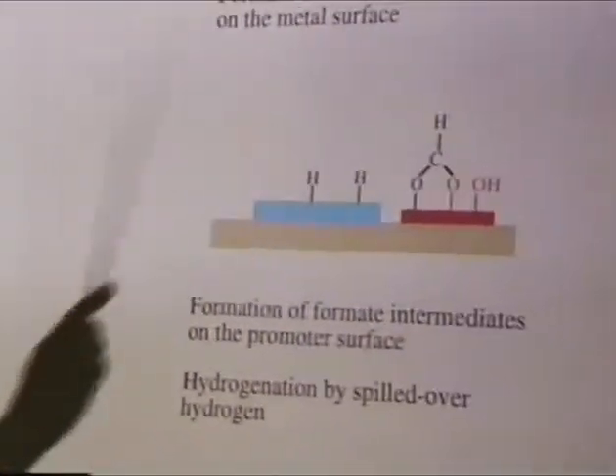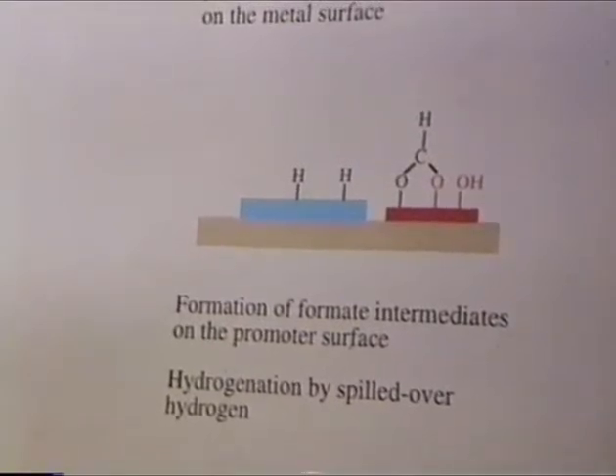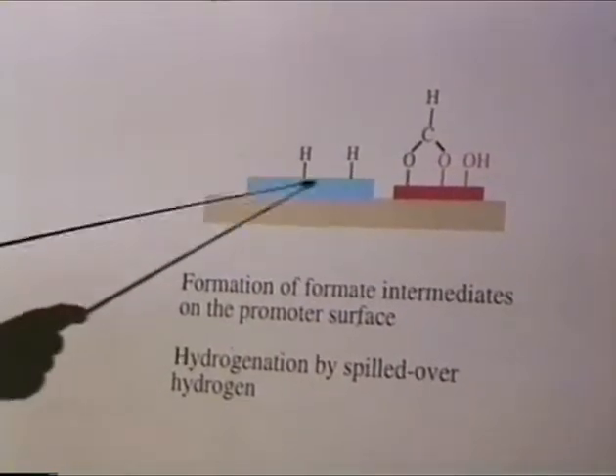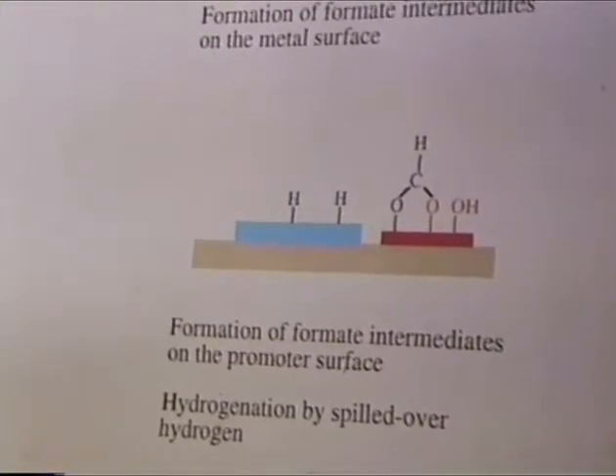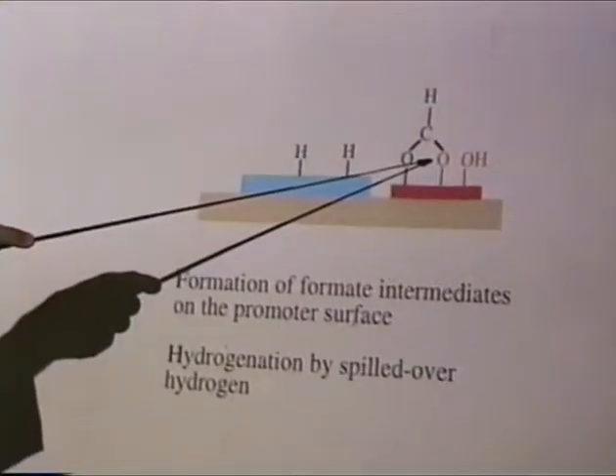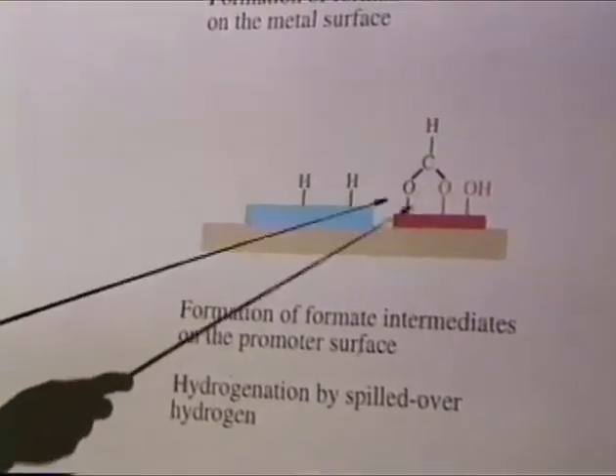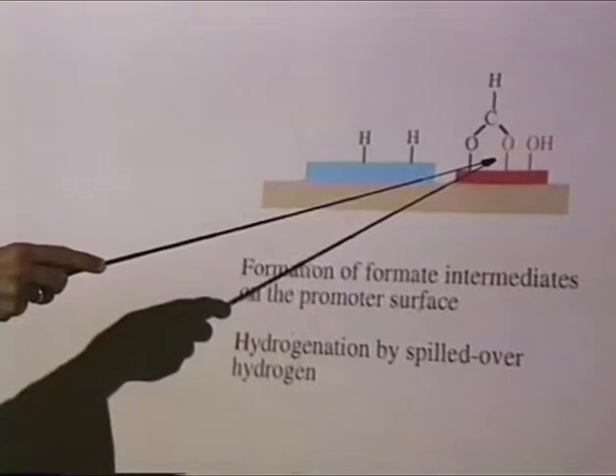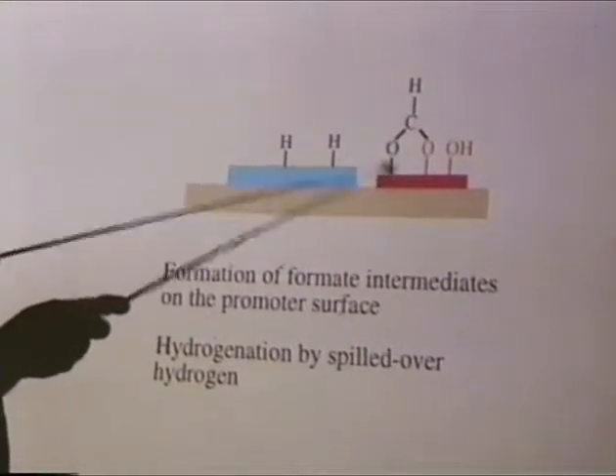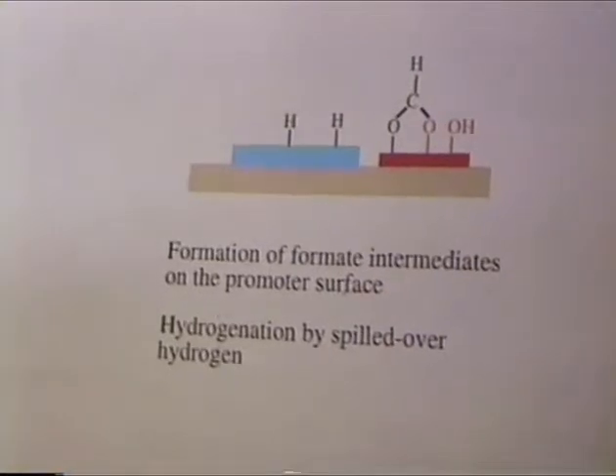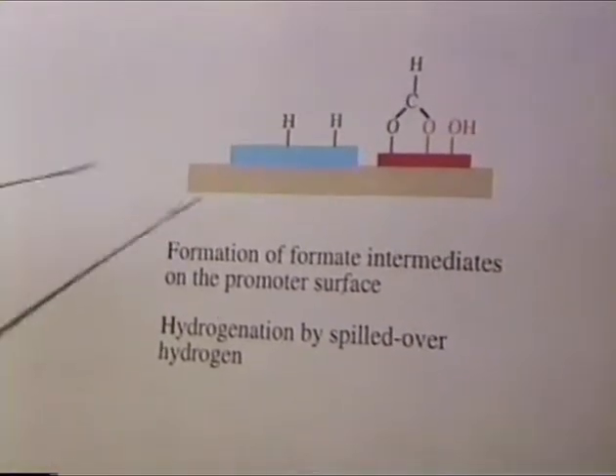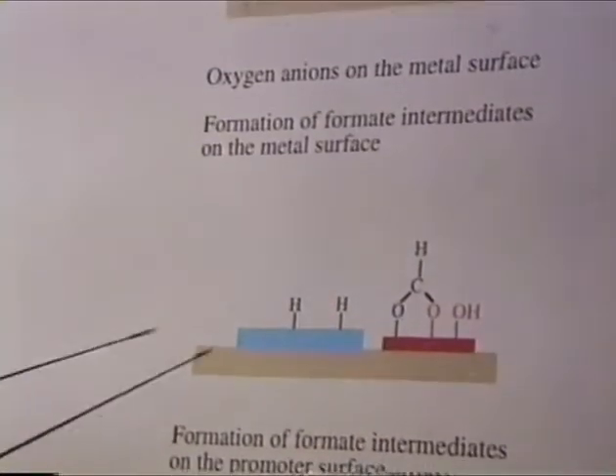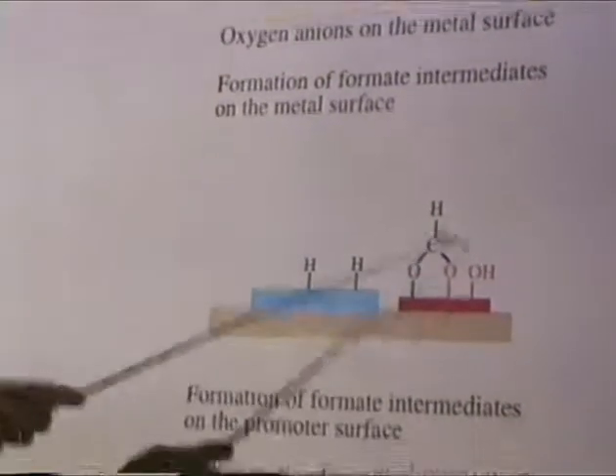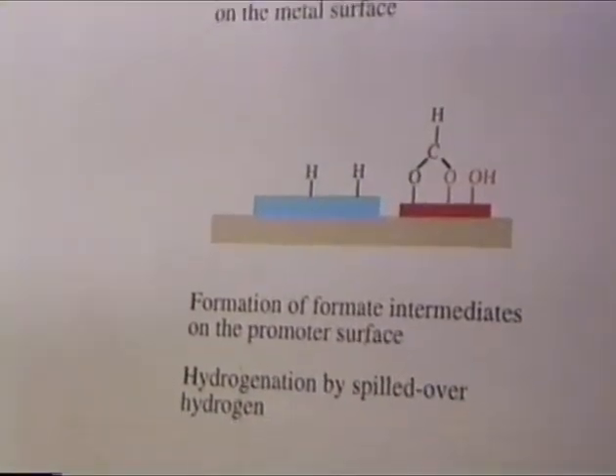A really different mechanism is where the promoter oxide is really separated from the metal, and now you make the formate on the promoter oxide, without any palladium or copper or whatever metal taking part in the formate formation. And then the question is, how is this hydrogenated to the methoxy and then onwards to the methanol? Is that by spillover of hydrogen in that direction, or is there a spillover of the formate to the metal and then the hydrogenation? Or is there a third route? In this case, of course, if this is very close, you can have the hydrogen spill over that way or the formate spill over this way. You can still believe it more or less.